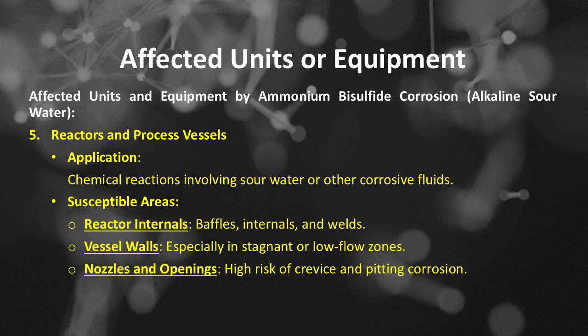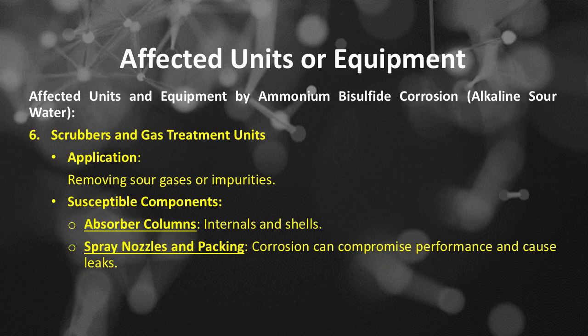Affected units and equipment by ammonium bisulfide corrosion or alkaline sour water. Number 5 is reactors and process vessels. The application of reactors and process vessels is chemical reactions involving sour water or other corrosive fluids. The susceptible areas include reactor internals, baffles, and welds; vessel walls, especially in stagnant or low-flow zones; and nozzles and openings, with high risk of crevice and pitting corrosion.